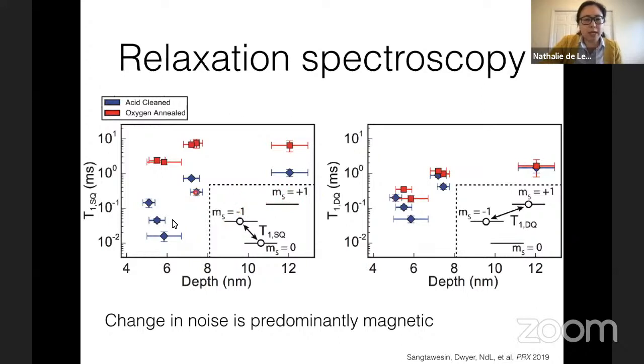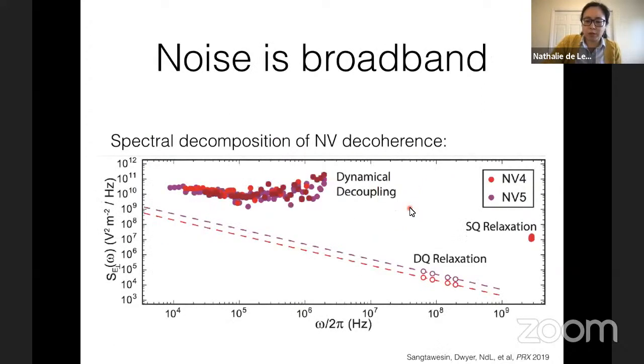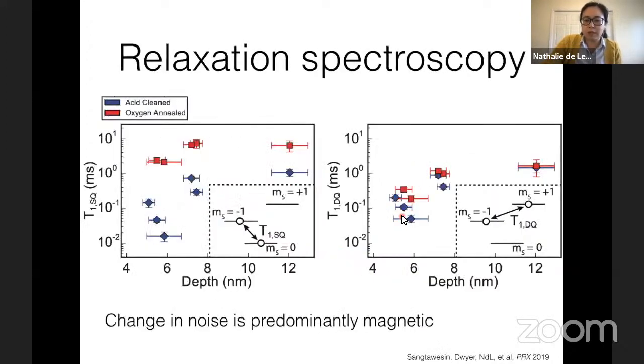So what we see is that if we look at our single quantum T1, we get this very large difference as we do this last oxygen annealing step. Whereas if we look at the double quantum T1, it's a much smaller difference. So this indicates that the change in noise that we see is predominantly magnetic.